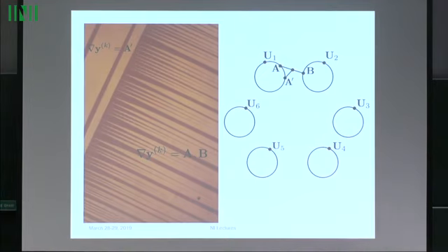In this case, actually, you can vary the volume fraction. So you can vary that point, and at every choice, there's exactly one matrix over here which is rank 1 connected. That's also seen in experiments, the fact that you can vary the volume fraction here. And this interface changes a bit as you vary the volume fraction.